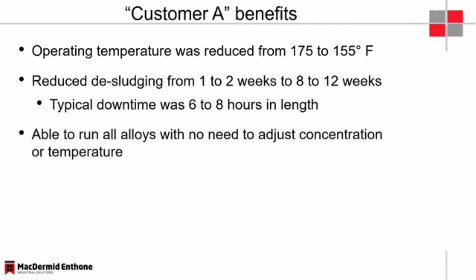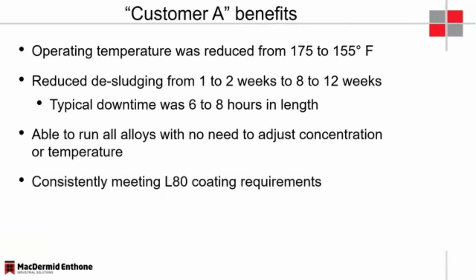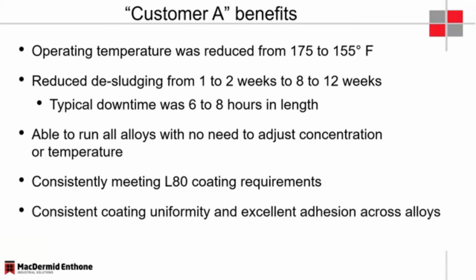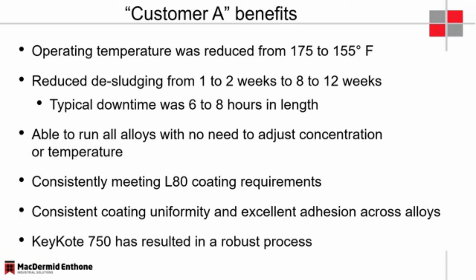The process has also enabled them to run the alloys that they have to deal with without the need to adjust concentration or temperature. And it has eliminated the inconsistency in meeting the coating weight requirements for the L80 alloy. And finally, it has resulted in a process that delivers consistent coating uniformity and the adhesion that they expect and require across the various alloys that they have to process. And so after a year plus of being in place, the 750 process has resulted in positive changes for customer A and resulted in a robust process.